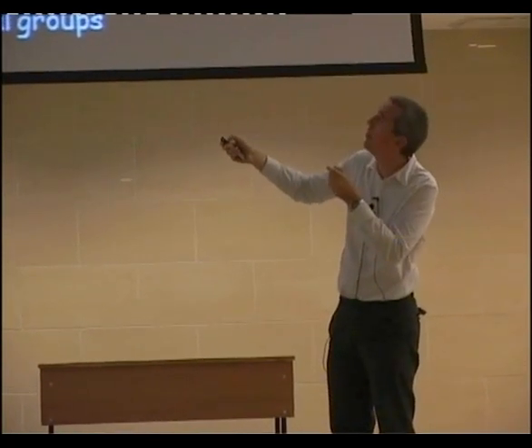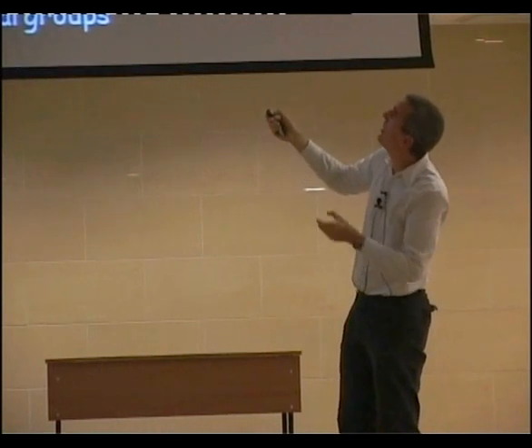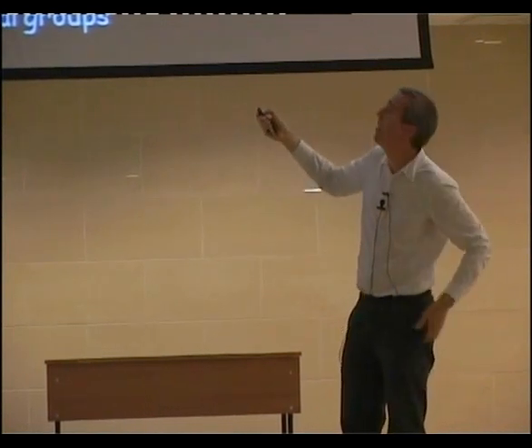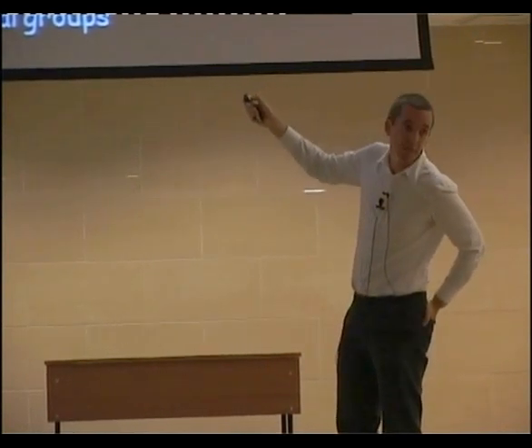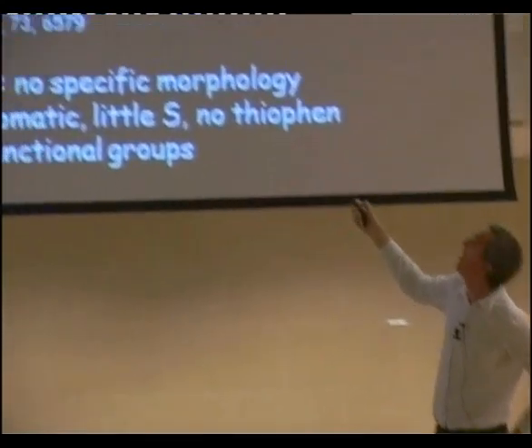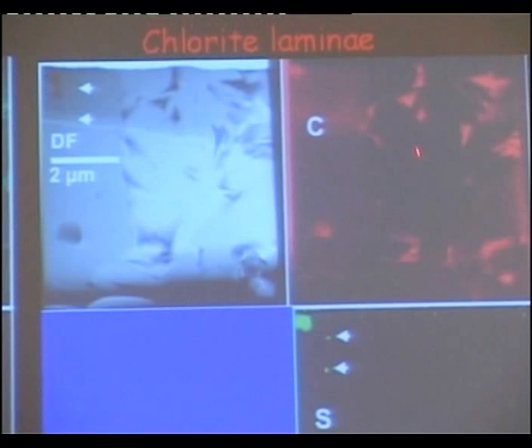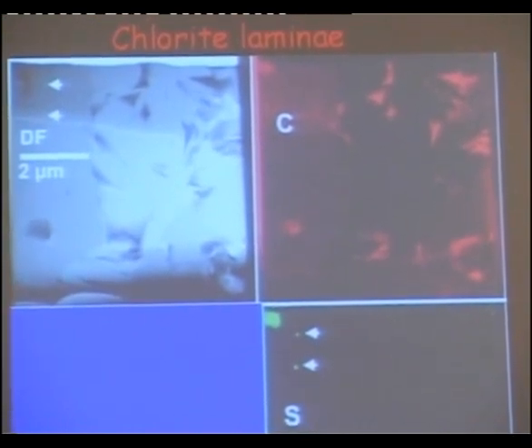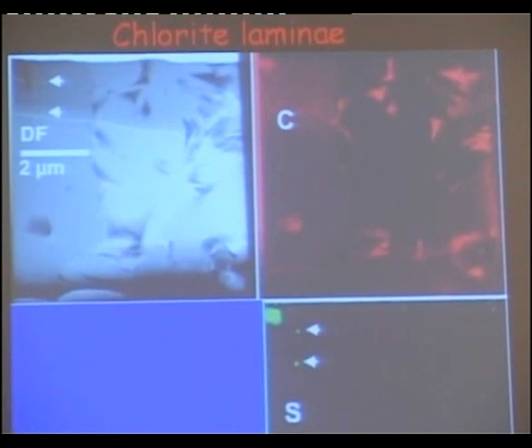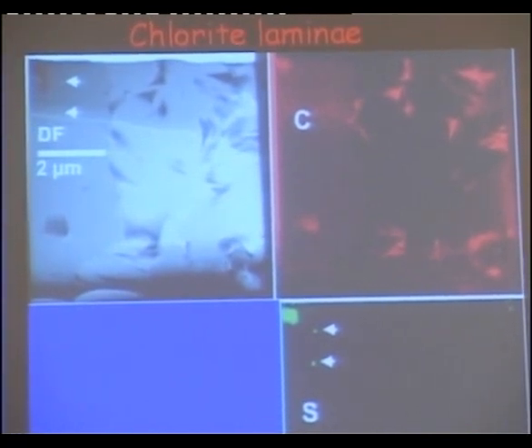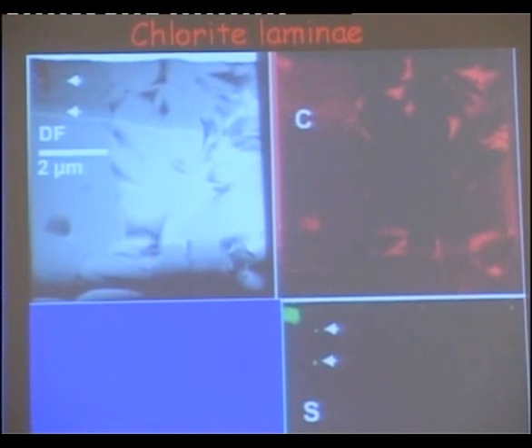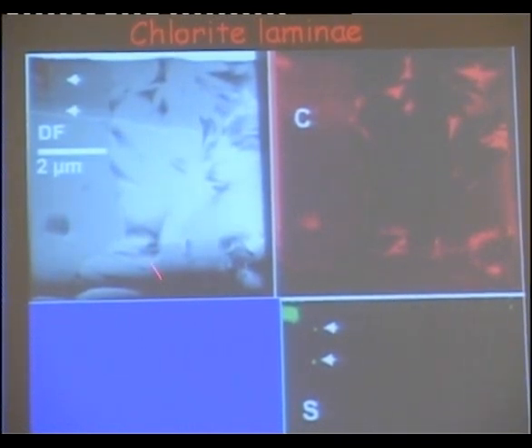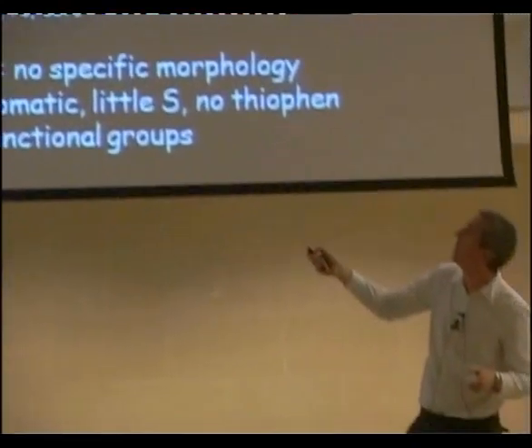Now if we move a few microns away from the carbonate laminae, here, this is the chlorite laminae. If we map this chlorite, we see carbon as well. It's here in red. But this time, there's no sulfur associated with this carbon. So we have organic carbon in the carbonate laminae, and we have organic carbon in the chlorite laminae, but they are not the same carbon. One is rich in sulfur, the other one is poor in sulfur.